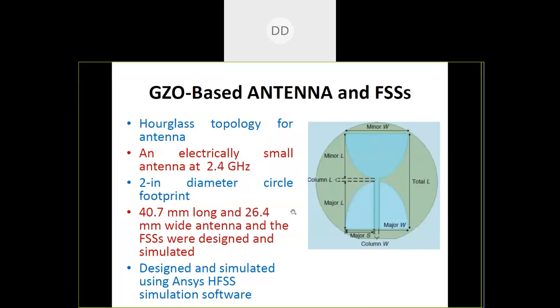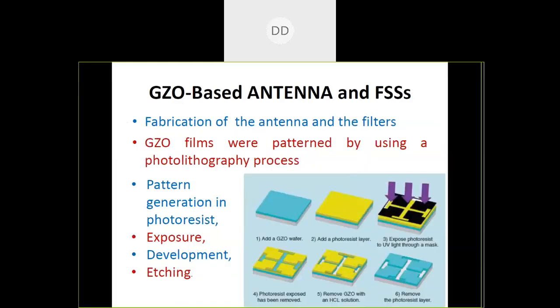For designing the antenna, because they have to fit it in a 2-inch diameter circle footprint, the size of the substrate was 2 inch in diameter. So they have to design a small antenna. They proposed this hourglass topology for the antenna. The dimensions are 40.7 mm by 26.4 mm. This was the size of the antenna which has been designed. These FSS and antennas have been designed using HFSS software, which was proposed for the simulation and design of these different surfaces and antennas.